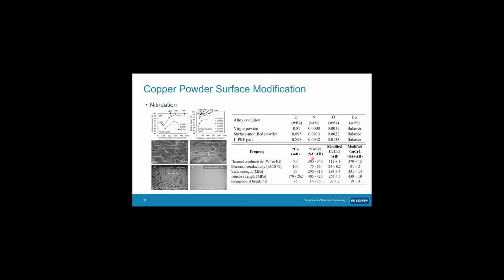So that also means we can vary the ratio of metallic chromium to chromium nitrides. And we know also how deep a laser beam can penetrate in chromium nitride and chromium. So we have a fairly good idea of how we should surface treat these powders in nitrogen.